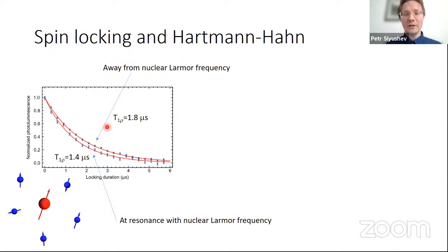If you match the Rabi frequency to the Larmor frequency, we bring the two systems into resonance and allow cross relaxation. That's why instead of decoupling, we simply lose the coherence. That happens if you have a nuclear spin bath, where coherence is lost.